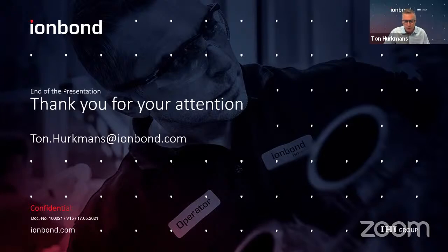The columnar structures, I must admit, PVD coatings are typically deposited columnar, and there are, let's say, pathways between the surface of a coated product and the product before coating. So these are very tiny channels, so-called pinholes. They can cause some excess of corrosion media to the base metal that has been coated, but percentage-wise, this is still really low. It's still less than 1%, is my guess, if you would translate it in percentages. Extremely low, but I cannot say it's 100% not existing either. But again, it depends, like you said, Peter, what technology and what coating you are aiming for.